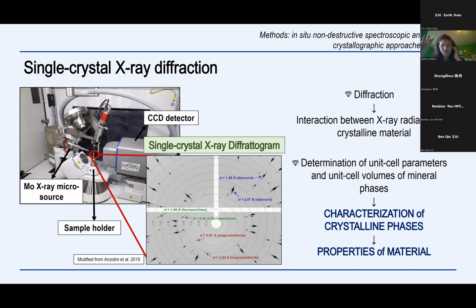As I mentioned before, at the University of Padua, we use a special single crystal X-ray diffractometer. This diffractometer is composed of a molybdenum X-ray microsource, a microsource because it allows us to study very tiny material within a host. The second important element is the CCD detector, a very sensitive CCD detector that allows this diffractometer to detect also the weakest diffracted peaks derived from the inclusions analyzed within the diamonds or within a host in general.